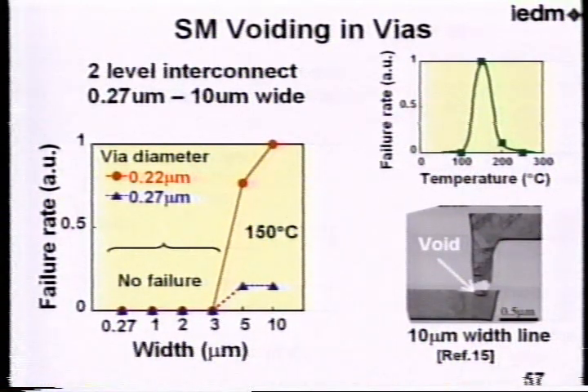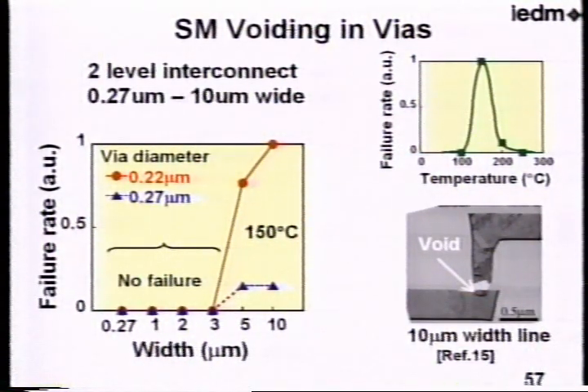Next, I'll talk about stress migration voiding reliability problems. This figure shows the via chain's failure rate against the width of interconnect. As you can see, if the line width is bigger than 3 micron, the failure rate was much increased, like this. And also, it has a dependence of via diameter. And you can see in this failure, you can see a void at the bottom of copper interconnect. And very interesting thing is that this kind of failure has a strong temperature dependence. The failure rate has a maximum at around 150 degrees C.